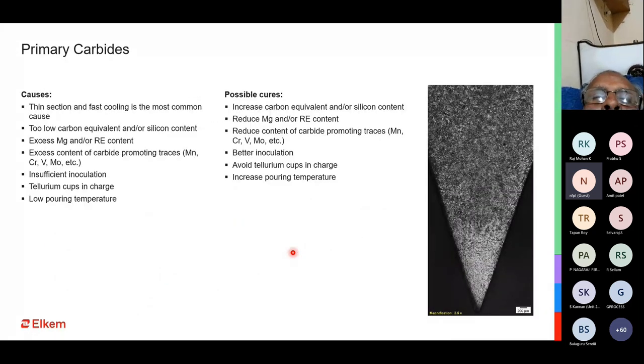What are the causes for these primary carbides? One of the causes is thin section and fast solidification, meaning you do not give enough time for the carbon to come out as graphite. When you have a very poor carbon equivalent or silicon content, it means you do not have enough graphitizers. When you have a very high magnesium percentage, it can give you carbides. When you have a very high percentage of carbide promoting trace elements like chromium, vanadium, molybdenum, etc., it can give you excessive carbide. When you do not have a sufficient amount of inoculation, meaning you are not allowing enough nucleating sites to develop, then you will have a lot of carbides.